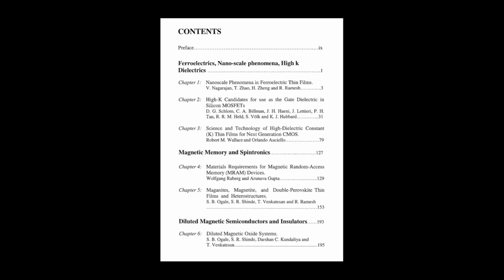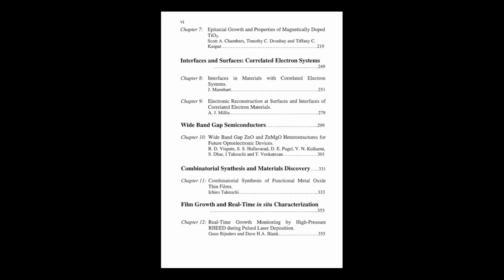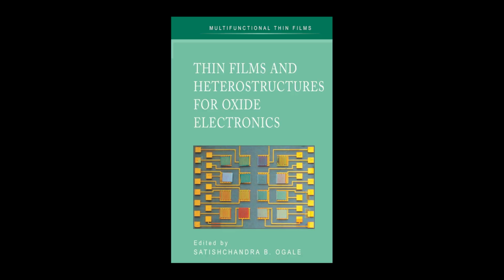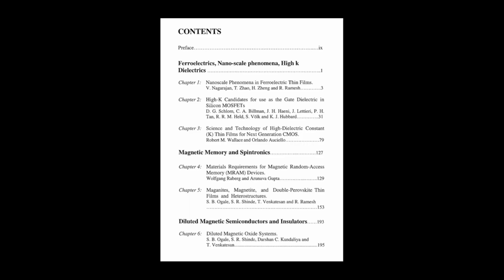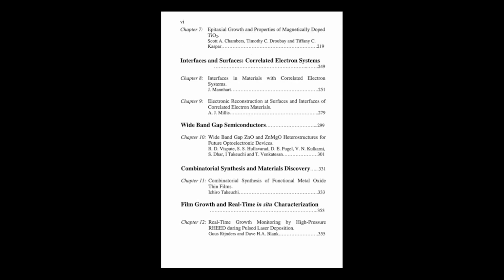How could an interface make an insulator metallic? We'll take a classic Mott insulator, like nickel oxide, NiO. It's an insulator because the Hubbard U is large compared to the electron bandwidth W. But right at an interface, maybe the coordination number of Ni atoms is reduced or screening changes. This could effectively lower the U/W ratio enough to push the material across the phase boundary into a metallic state, just in those few atomic layers near the interface.